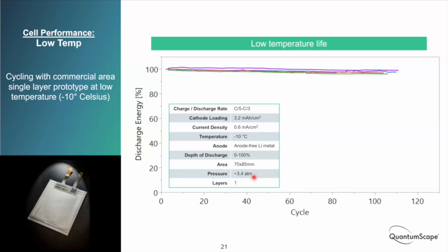Next, let me come back to this pressure point here. Many cells need some pressure, even lithium ion cells have some pressure to keep all the layers in contact with each other. And as things swell and expand and contract, as lithium moves in and out of the different layers. Solid state cells are often tested at relatively higher pressures to keep all the layers in contact with each other. The results that we've been using in the range of 3 atmospheres are, I think, an achievable pressure when you put it into a car.